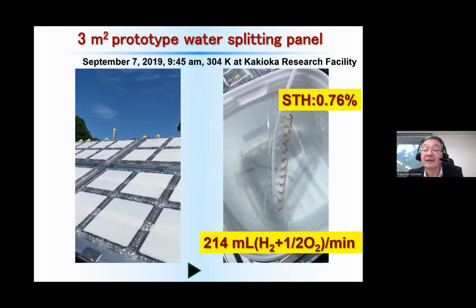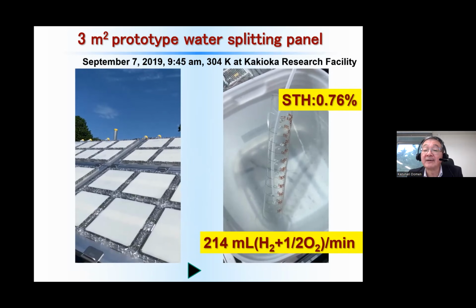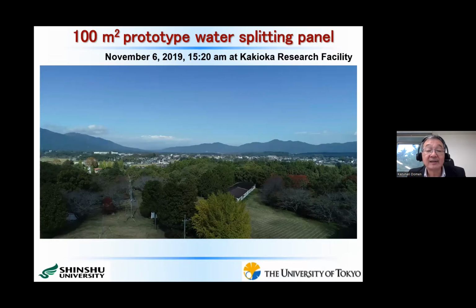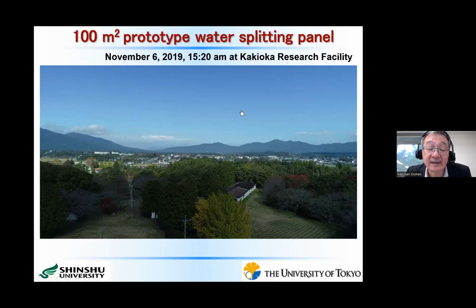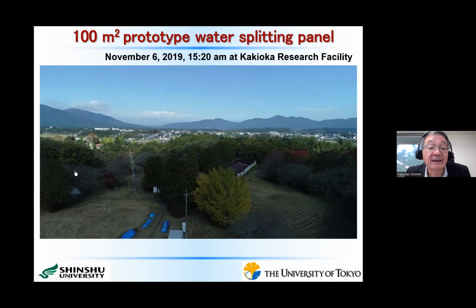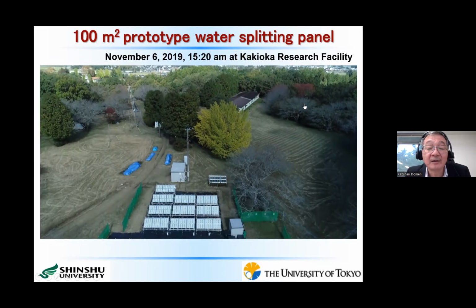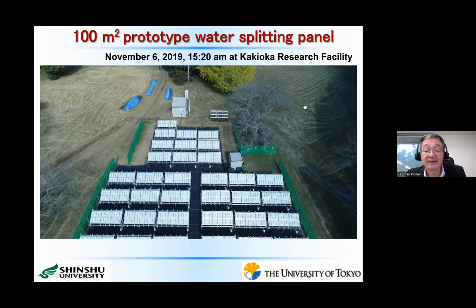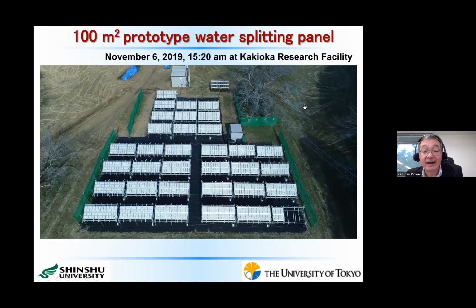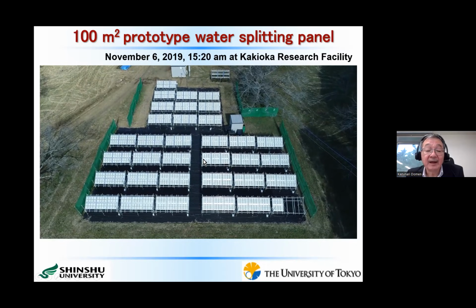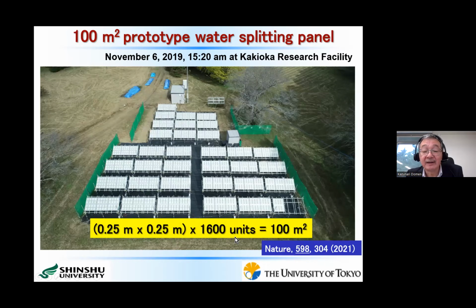In this case, the solar to hydrogen energy conversion efficiency was about 0.76%. So we decided to construct the 100 square meter system at Kakioka Research Facility, the University of Tokyo's campus. On this small hill, there is a flat place as shown here. From this one, we actually used 1,600 water splitting panels to cover the 100 square meter light receiving